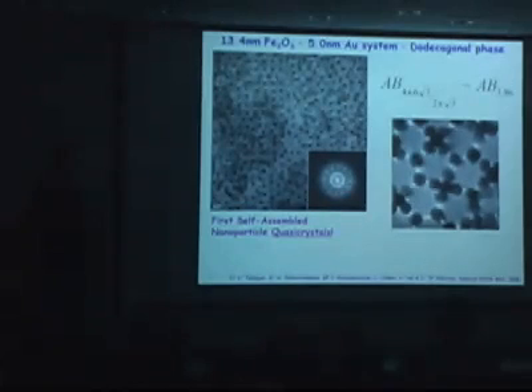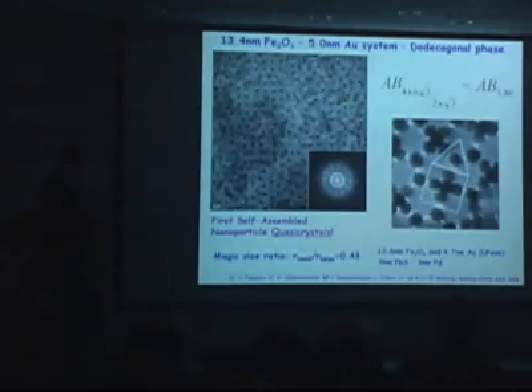And what we built can be rationalized as an arrangement of squares and triangles. The first nice thing to be proud of was that prior theoretical works totally overlooked this type of packing. And the second important thing was that we found the key to forming these structures was really the particle size ratio. Once we made other materials with this size ratio, you can self-assemble them.